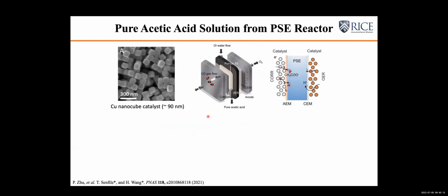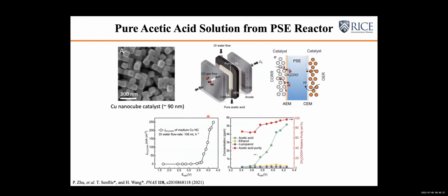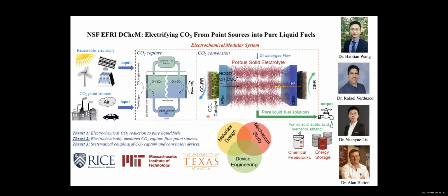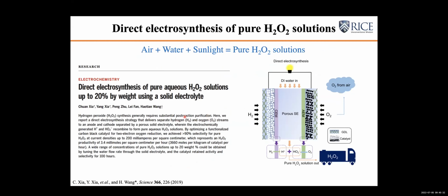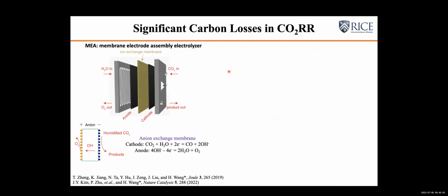Of course, this solid electrolyte device design can be adapted to many different types of electrochemical synthesis. If you change the catalyst to an acetate selective catalyst, you can generate high purity acetic acid. If you want to generate hydrogen peroxide from oxygen reduction, which is different from CO2 reduction, but they share almost the same mechanisms, you can use the solid electrolyte device to generate high purity hydrogen peroxide solutions.